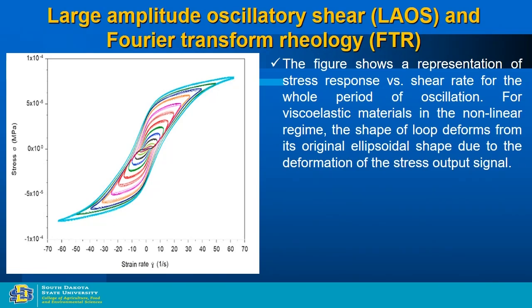Yes, Rubati. The parameters that we have to fix for this kind of test, for example, we have to keep a particular strain and check the stress like that. That is true, yeah. And you also do the same thing like a frequency sweep, and then a stress sweep and stuff like that. But whatever you do in small amplitude shear, here we are looking at large amplitude oscillatory shear. Previously, the thought process was that we are looking at the micro scale analysis, what is happening at the micro scale level, so that way we are trying to understand what's happening without damaging the sample. Now in large amplitude oscillatory shear, we are damaging the sample, but that's okay. That's what happens in actual sensory analysis, right? So we feel that this way the correlation is better.